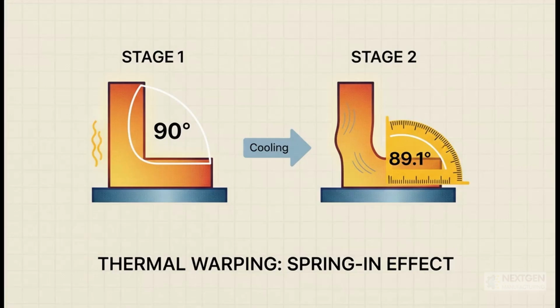And this isn't just some theoretical problem. It has a very real, very visible effect called spring-in. If you make a part on a perfect 90-degree tool, those residual stresses will literally cause it to warp inward as it cools. You take it out and measure it, and it might be 89.1 degrees. The part has literally changed its own shape after you finished making it.